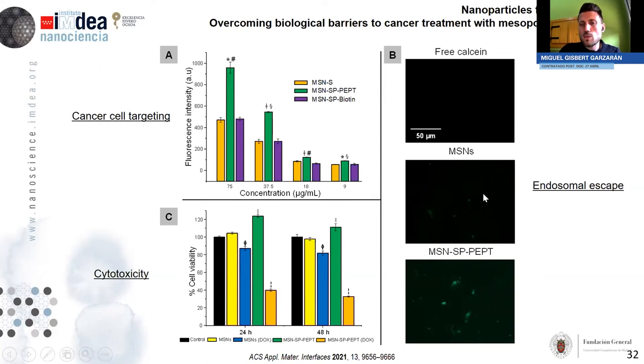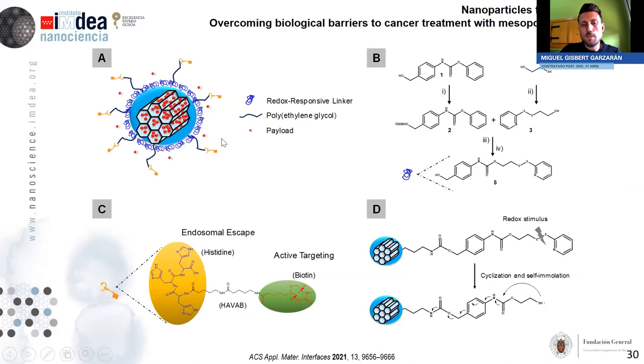If we introduce mesoporous silica nanoparticles without any functionality and calcein, we will see small dots of calcein. And the reason for this is that one of the properties of calcein is that when it is at a very high concentration, it self-quenches, so we can't see its fluorescence. However, when the concentration is not so high, we can see the fluorescence again. And this is what happens in the case where we have this complete system with this molecule that is able to induce the endosomal escape.